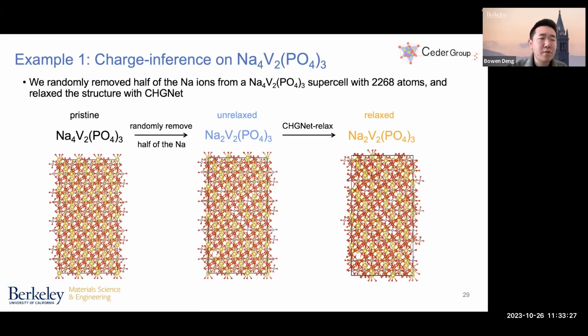So after talking about these benchmarks we have done with CHGNet, I want to show you a few applications where we really apply CHGNet to solve problems in energy storage materials. The first example I want to show you is how we do charge inference in these NVP NASICON structures. We randomly removed half of the sodium ions from an NVP supercell with more than 2,000 atoms, shown on the left, and we relax the structures with CHGNet. The pristine, unrelaxed, and relaxed structures are labeled in black, blue, and orange fonts.